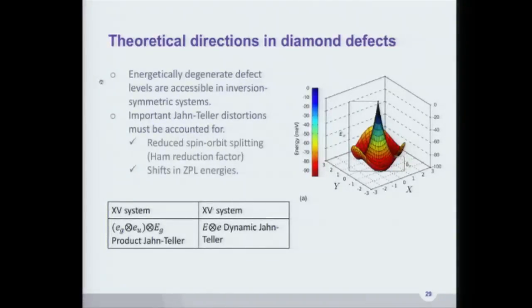And you don't want to see too much distortion. But of course, when you implant something giant like tin or lead into the material, you expect that it will distort things, right? That's our intuition, and it turns out to actually be true. In the neutrals, we see the product Jahn-Teller, which is essentially a product of the dynamic Jahn-Teller, which is what you see in the negative color centers. So this is something that is now implemented in our method.